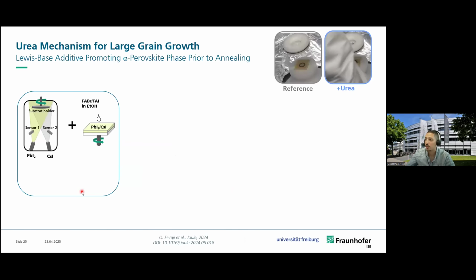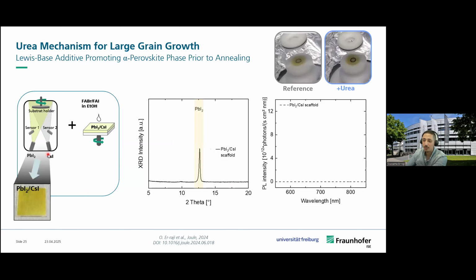So in terms of the perovskite grain growth, in order to understand the mechanism a bit, we try to track the different phases that evolve during the different fabrication steps. So here you can see the lead iodide, cesium iodide evaporation. After we evaporate, we have a relatively yellow film, as you can see, dominated by lead iodide. We have a strong peak here in XRD. We have no photoluminescence response because we don't have any photoactive phase.